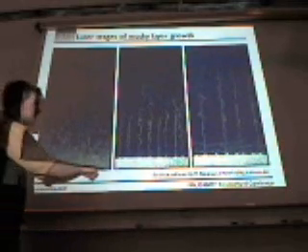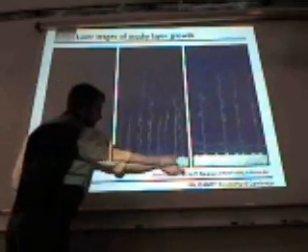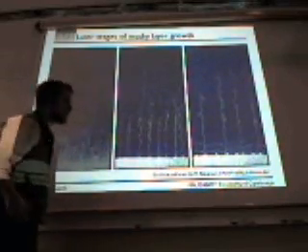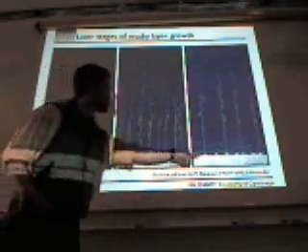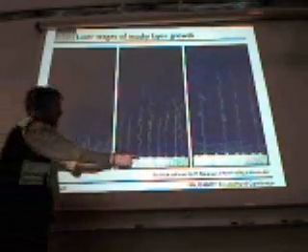So just to show, if I take this experiment to longer times yet, here you're starting to see those crystals at the bottom of the frame with this boundary layer mode of convection. And then jumping a fair bit further in time, here's this reactive porous medium, this mushy layer, with a very dramatically different style of convection emanating from the top, and at yet another later time. That style of convection is dominated by these thin plumes originating from localized patches within the ice. And so the flux of, in this case, fresh fluid from the ammonium chloride mushy layer, or in the case of sea ice, the flux of salt from that sea ice mushy layer, is dominated at later times by these plumes.